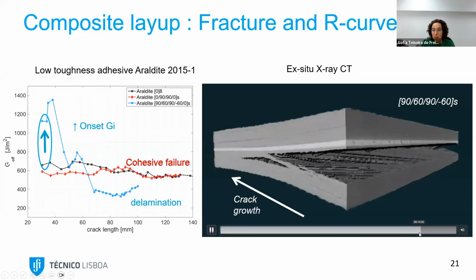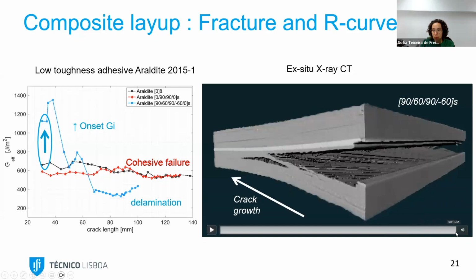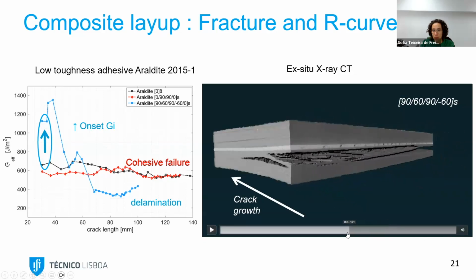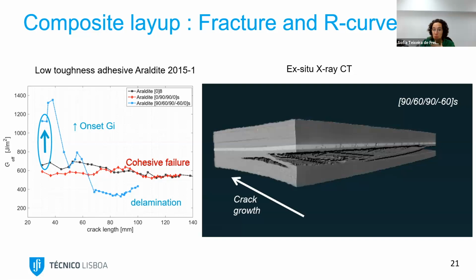And indeed, what we see is that you see a lot of crack fronts. You see a crack front here, you see a crack front there, you see a crack front there and there. So there is a lot of crack deflections and a lot of fracture surface that we're opening at this location.